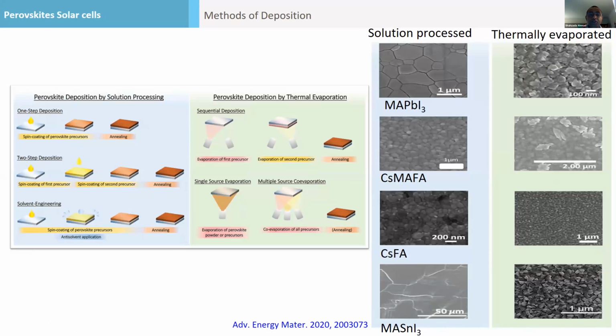There are two ways of deposition. What we do is generally a solution processing route, but there are also very good groups which are working on thermal evaporation, and they have also reported very good efficiency. The good thing about thermal evaporation is that you can control the thickness to a nanometer range, because there is a quartz crystal microbalance associated with it, and you can precisely control the thickness. In our case, we don't control it in the wet chemistry process. We are always 5 nanometers or 10 nanometers plus or minus, even if we use the same composition or same reference.